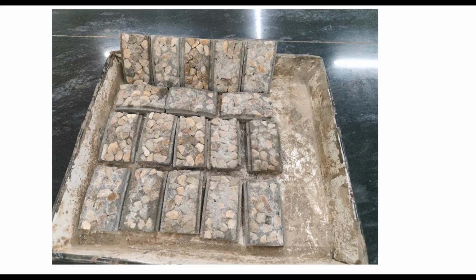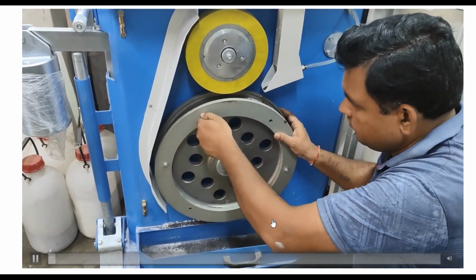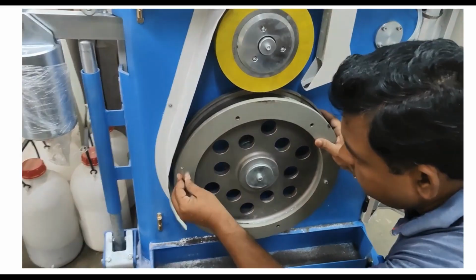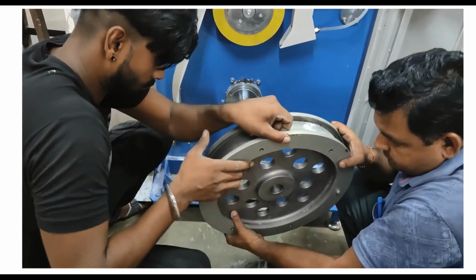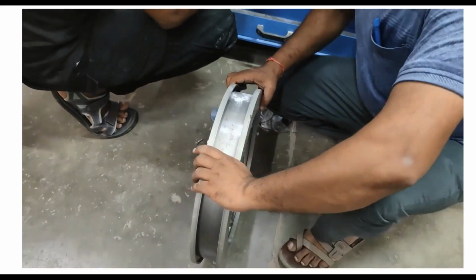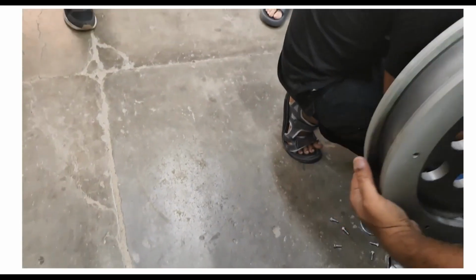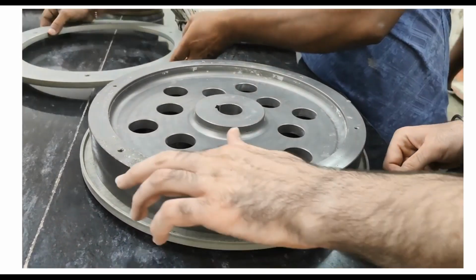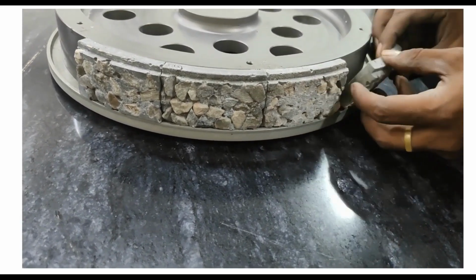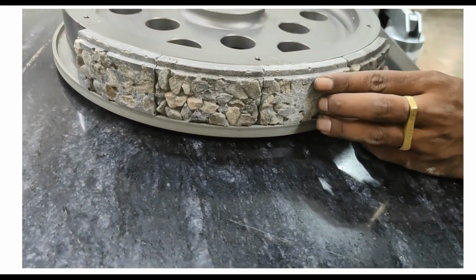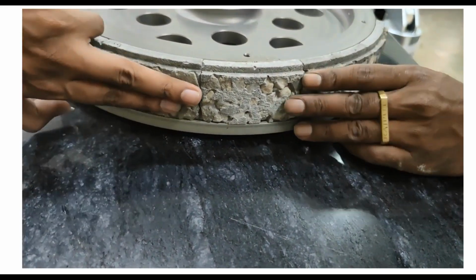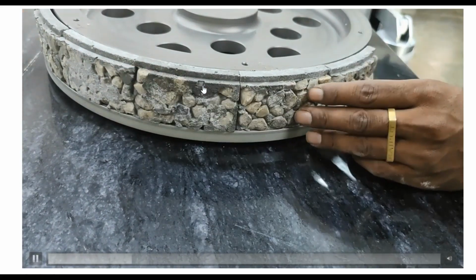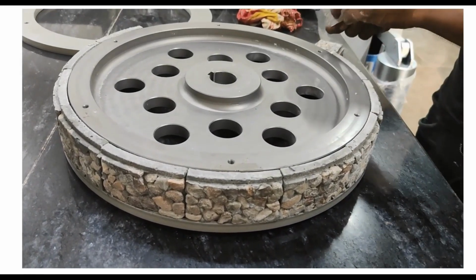Now, once you are ready with 14 specimens, either using cement sand paste or using some adhesive material, then these are to be fixed on the larger wheel of the machine. So take out the wheel of the machine carefully and place it on a surface, remove the upper ring, and then place or fit these specimens one by one. Care should be taken to have the smooth surface and no gap between the specimens. There should be no gap here between two specimens. Once you fit all 14 specimens around this wheel,